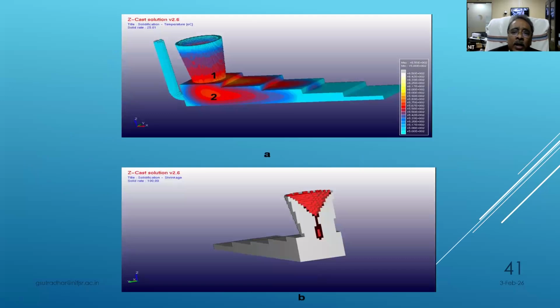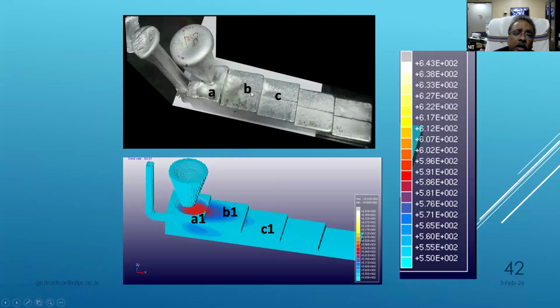This is the normal casting situation, where this is the thickest zone, that means last to solidify, and this is the thinnest zone, because the direction of solidification is along this arrow. This is the part that is last. Now, if you take a cross section of the riser, the solidification will be like this. This is the part that solidifies last, and it will shrink like this towards the center of the riser neck. Now this is for the aluminium. It's a real picture he has taken: this is the highest part, with little shrinkage with that small 20 millimeter base.